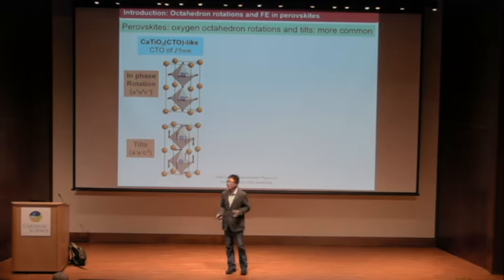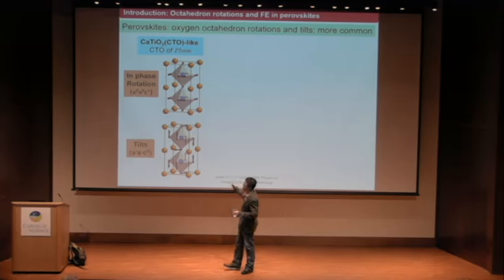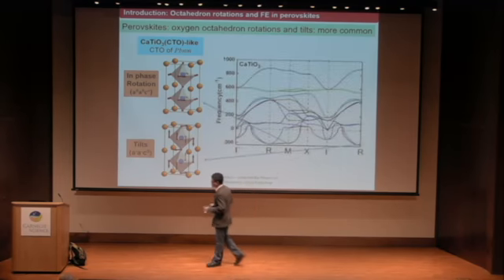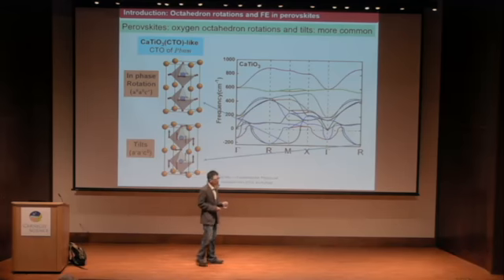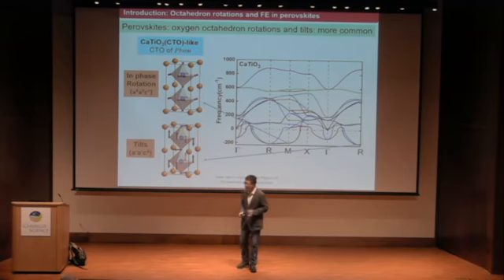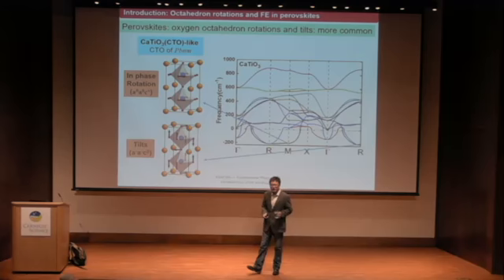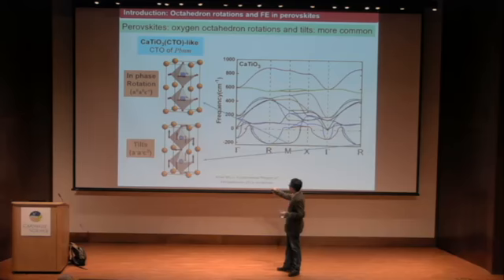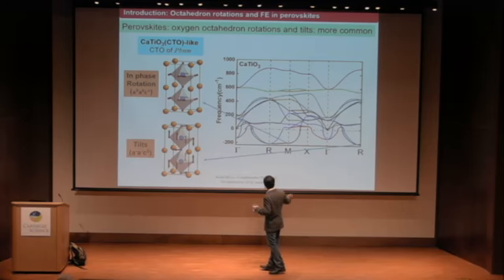The typical material having this rotation pattern is calcium titanate, for example, with a Pbnm phase. We also know that if you try to understand the origin of the rotation patterns, it actually originates from Brillouin zone boundary instabilities. For example, the in-phase rotation is from the M point, and the out-of-phase rotation, or tilt, is from the R point.